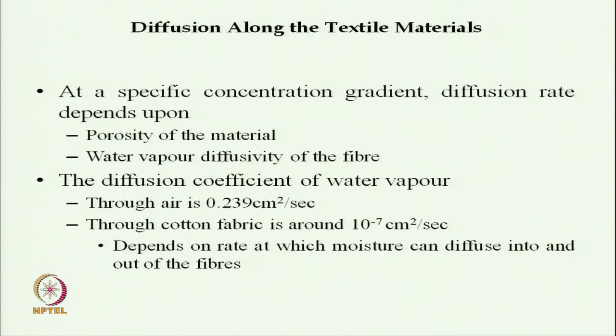So, as far as the non-Fickian diffusion and Fickian diffusion, the diffusion through the air, the diffusion coefficient here is 0.239 square centimeter per second. And if we see through cotton, it is very, very slow, it is of the order of 10 to the power minus 7 square centimeter per second. This is very slow. So, that is why for fast release of moisture vapor, we must create pores in the sports textile. Otherwise, it will be very slow.